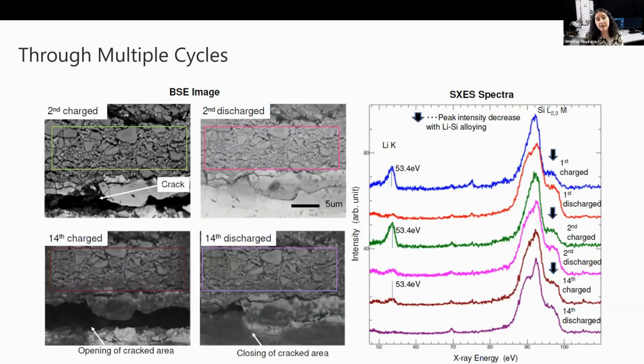And the silicon layer that became amorphous in the first cycle remains amorphous and was still able to absorb lithium during the charging and repeatedly form lithium-silicon alloys after the second cycle. So starting with the second cycle, the silicon remains amorphous throughout both charging and discharging. In this experiment, we went through 14 charge-discharge cycles. In this graph, we're showing the data for the first, the second, and the 14th cycle for both charged and discharged. And looking at the lithium peak in the data, we can see that the peak intensity of the lithium decreases with the lithium-silicon alloying, reducing significantly by the 14th cycle.